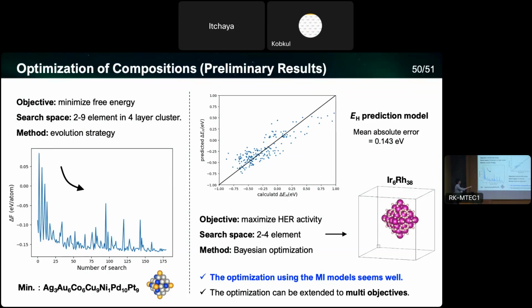And we also make the prediction models for hydrogen absorption energy in this case. Then from hydrogen absorption energy, we can evaluate the activity of hydrogen evolution reactions. So we maximize this activity using these clusters through the Bayesian optimization. Then we got iridium, rhodium, core shell alloys have the best